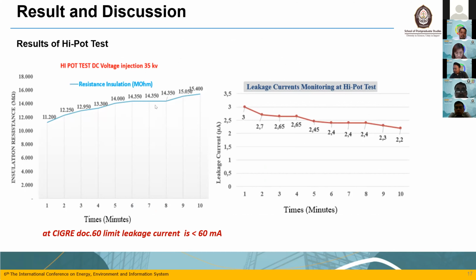From minute one until 10 minutes, there is an increase in insulation resistance because the injection of DC voltage after some time will reduce the humidity. Because injecting with 35 kV minute to minute will reduce the humidity. Maybe this answers it, Mr. Bayu.